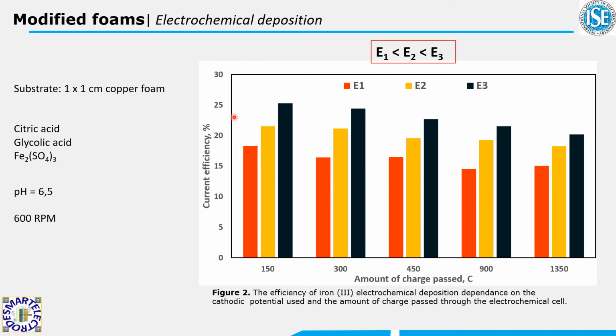Increasing the potential, the efficiency of the deposition slightly increases. At low potentials, the current density is quite low and the iron is heavily complexed with citrates and glycolates, hence the deposition is quite slow. As the deposition time increases, the deposition efficiency drops regardless of the potential used. The cause for this decrease is probably quite vigorous mixing. The flow of the solution breaks apart the dendrite-like structure on the surface, especially so with the longer depositions.